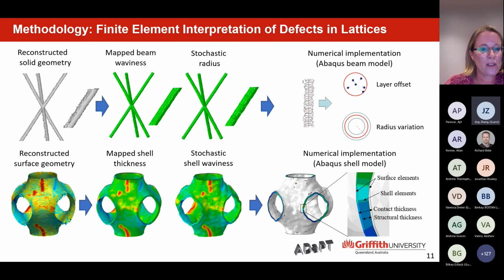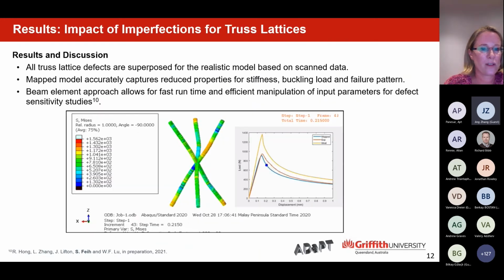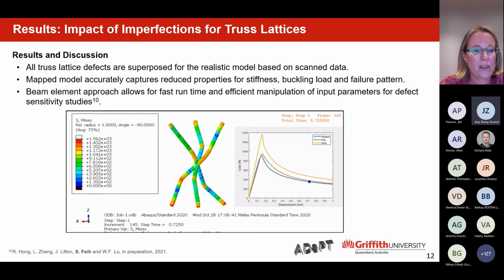Okay, so now some results. What does it actually look like? I'm showing here the buckling of a very simple unit cell, but this can easily be expanded to an array. All these truss lattice defects are superposed for the realistic model. You can see as the model is loading up, we're plotting stresses here, that those are not completely uniform. That is because there's radius variation, there's some offset in the radius.